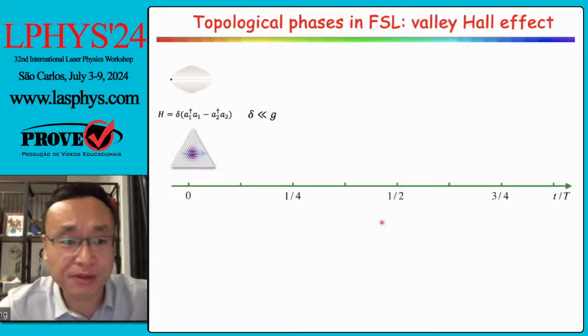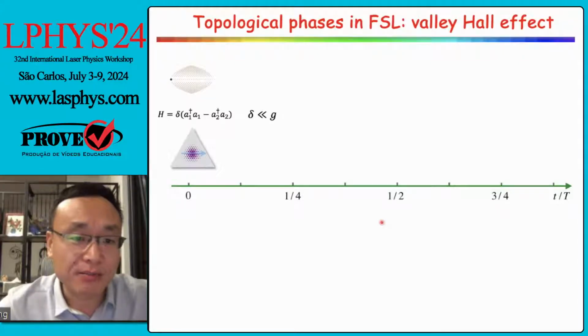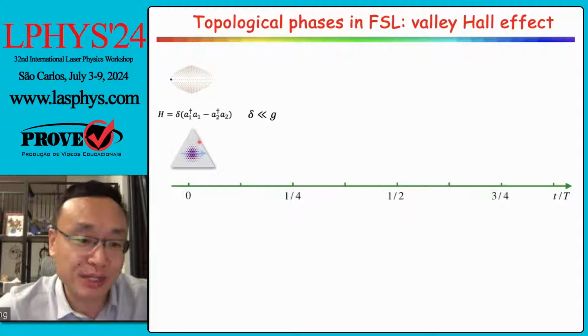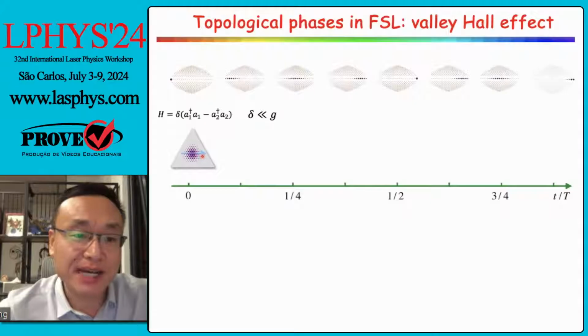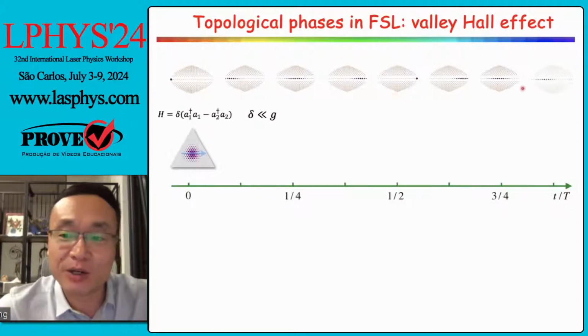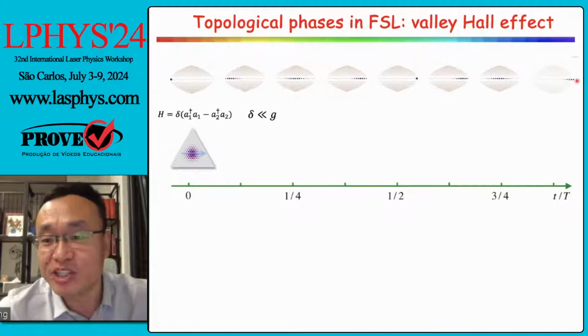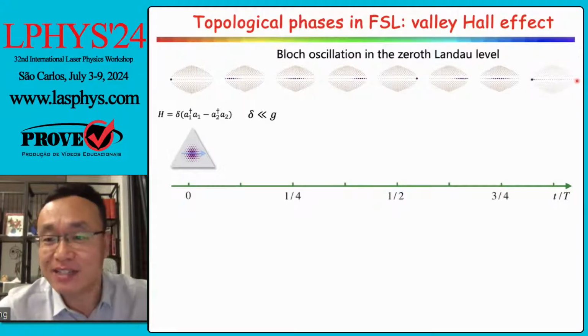And we can observe dynamics by applying an effective electric field to the system, because now we already have an effective magnetic field due to this inhomogeneous coupling. And if we detune two cavities, we are going to introduce a linear potential in the lattice. And what will happen is that for an initial state prepared in the 0th Landau level, we are going to find this kind of Bloch oscillations. The state is going to oscillate in this zero energy band.